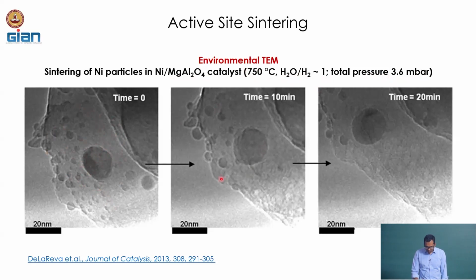But with time, we can see some of these smaller particles have come together to form a bigger particle, and with more time on stream, the smaller particles have almost disappeared. Their population has gone down significantly, whereas the population of the bigger particles has increased. So, this is one typical example of sintering, and we will see many such examples of how the transformation of the catalyst surface and the active site or active phase happens during the reaction, by taking examples of different catalyst and reaction systems and different characterization methods, mostly physical characterization methods.